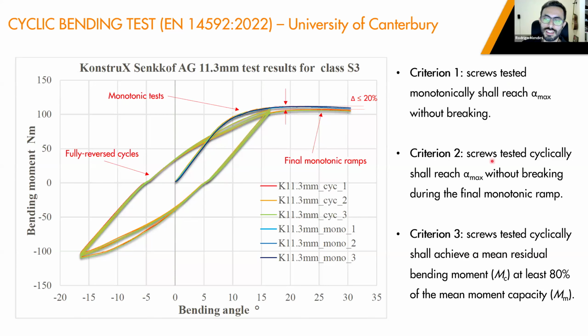In criterion 2, the screws tested cyclically shall reach this same alpha max angle without breaking during the final monotonic ramp. So even if they do the cyclic part okay, but on the final monotonic ramp they break before reaching this angle, they don't pass the test. And finally, criterion 3: the screws tested cyclically shall achieve a mean residual bending moment of at least 80% of the mean moment capacity. That means, like here on the final monotonic ramp, the maximum bending moment that you get on the cyclic test has to be a maximum of 20% different from the maximum reached on a monotonic test. So these are very strict criteria.